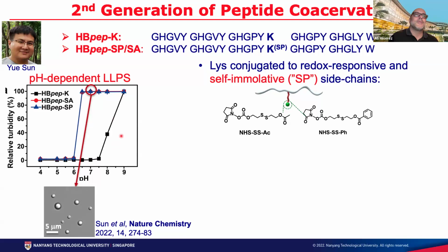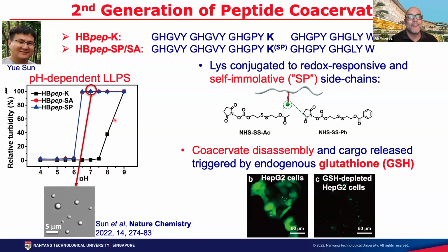But then once it goes inside the cell, those droplets will be subjected to this peptide called glutathione, which is highly upregulated inside cells, especially cancer cells. And what this glutathione does is that it cleaves this disulfide bond, and then you have this self-immolative chemistry. So the whole side chain is being removed and cleaved. And so you're back to the initial peptide, but now you are also at pH 6 or something. So it means that the peptide inside the cell will spontaneously disassemble and release the cargo.